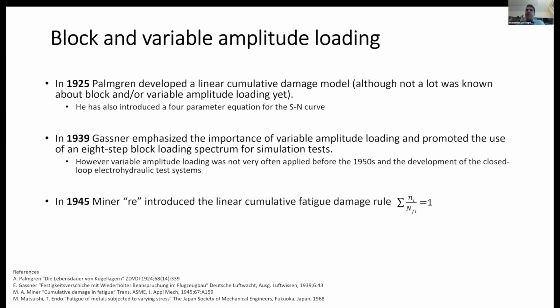Whatever we said up to now is related to continuous loading. You remember we have a waveform that is going up to failure, but in reality we know that the loading is variable. If you go outside, you see that wind has a variable waveform. Efforts were allocated to the investigation of this variable amplitude loading quite early, starting in 1925 with Palmgren, who developed a linear cumulative damage model to estimate the damage because of different blocks or variable amplitude testing. And you see again, he also introduced a four-parameter equation for the S-N curve. Gassner, later on in 1939, emphasized more the variable amplitude loading.